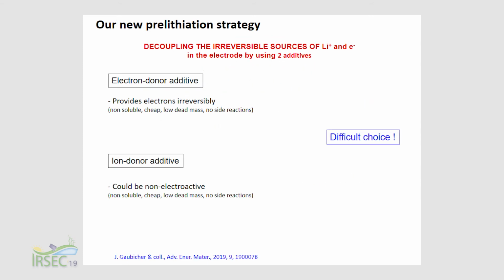So that's the reason why we propose a new pre-lithiation strategy in order to decouple the two irreversible sources of electrons and lithium ions, and we use two additives. So one additive is an electron donor. It has to provide electrons irreversibly during the first charge of the cell, and the other additive is a lithium-ion donor additive, and it could be chosen non-electroactive. So using two additives provides more flexibility, more versatility. Of course, it's quite difficult to choose which additive.